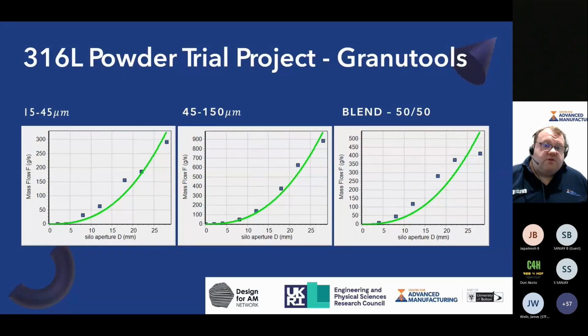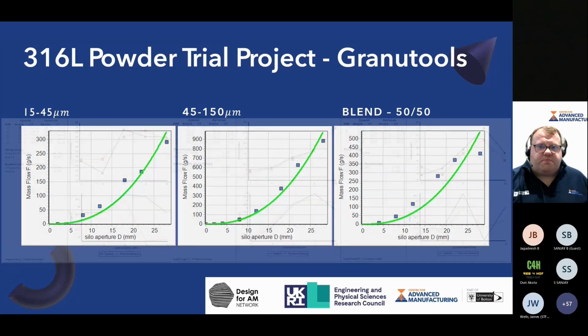In terms of the granule flow, we have multiple sizes of apertures, so it's the same test, just in different powder conditions. The blended powder was much slower and actually had, I guess, a worse fit in terms of following the trajectory expected. 15 to 45, relatively slow compared to the quick powder.